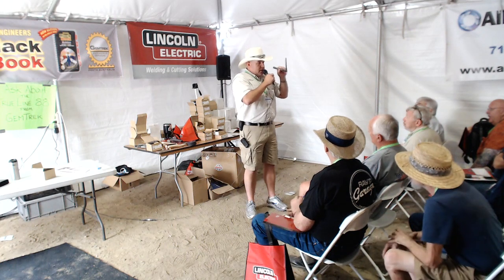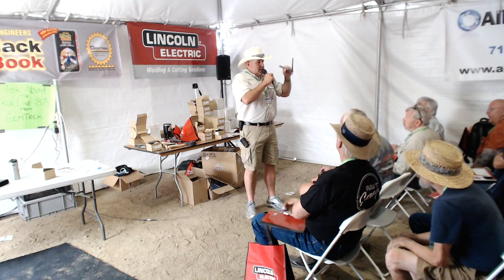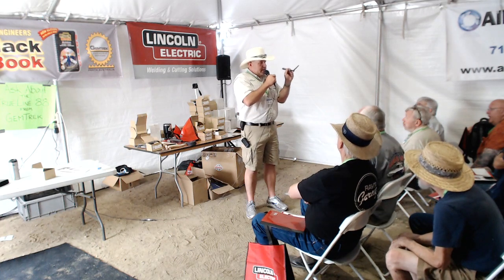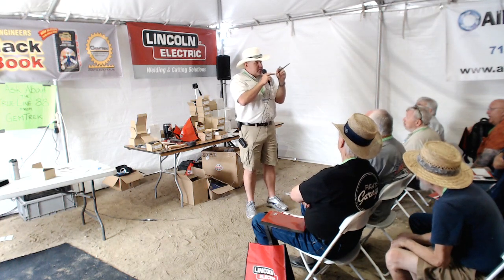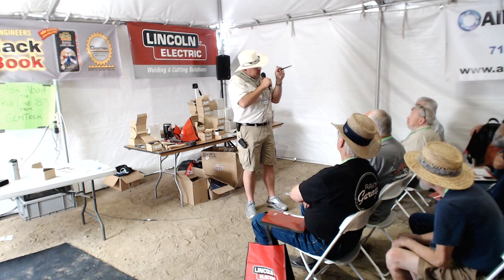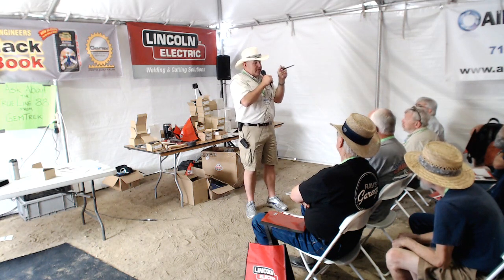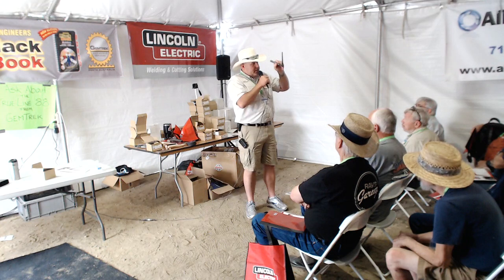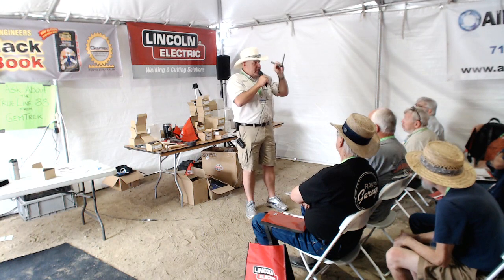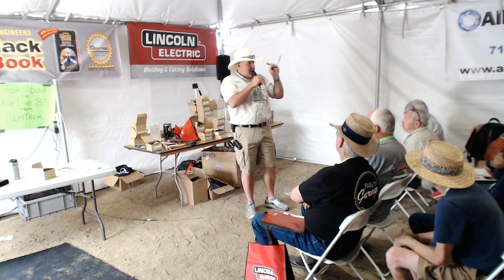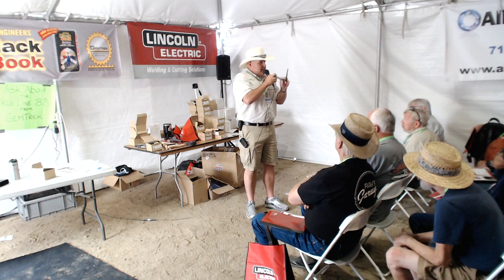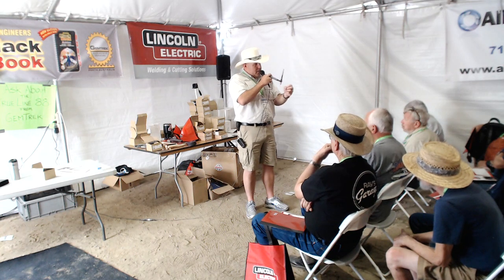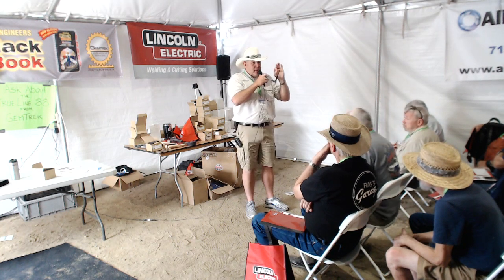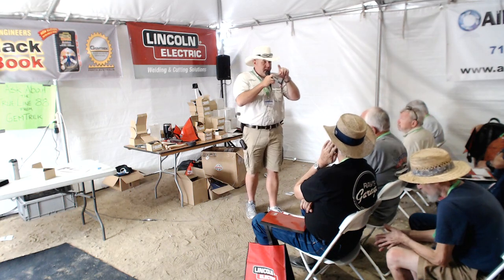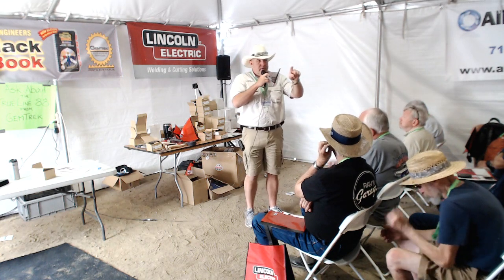Why does my weld look so bad? Because you did this. Because you want to see what's going on under that gas, and you put your head down. 90 degrees to the plate, 15 to 20 degree in the direction of travel. What it does is gives gas coverage out in front of your weld just a little bit. Why? Does anybody know why? Heat, but yes, gas coverage.